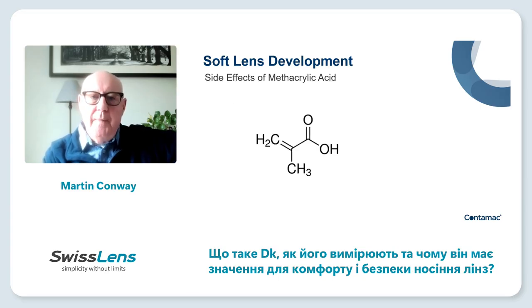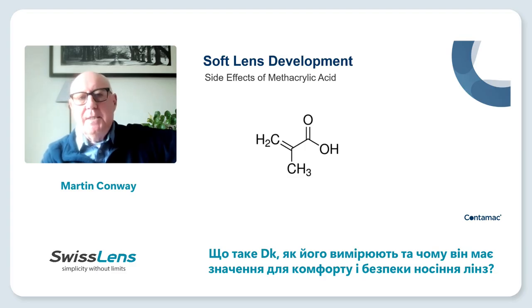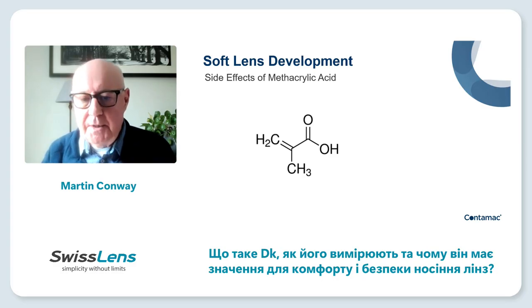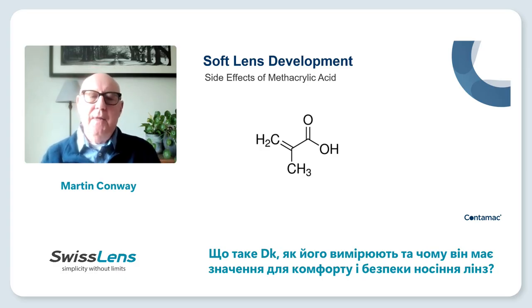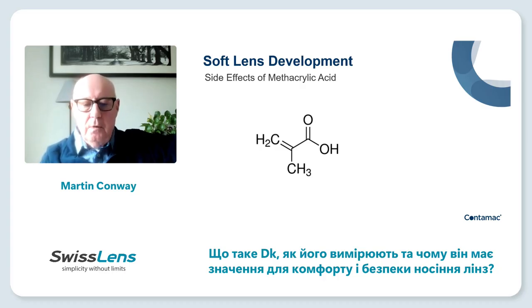If we look at the effects of methacrylic acid, it is an ionically charged monomer. It carries a negative charge. And these monomers within the matrix of the lens both have negative charges, and they tend to repel each other within the matrix of the lens. And therefore the matrix is forced apart and expanded, and this allowed more water to actually penetrate the matrix, hence increasing the water content. So the use of methacrylic acid forced the material into becoming ionic.